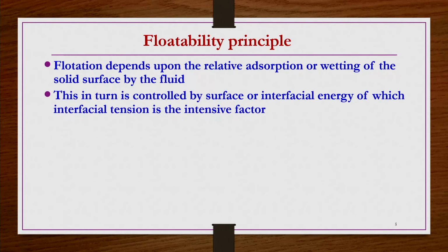Flotation depends upon the relative adsorption or wetting of the solid surface by the fluid. This in turn is controlled by surface or interfacial energy, of which interfacial tension is the intensive factor. So, the surface characteristics we have been discussing, this interfacial tension is the very important intensive factor that decides the performance of the flotation cell.